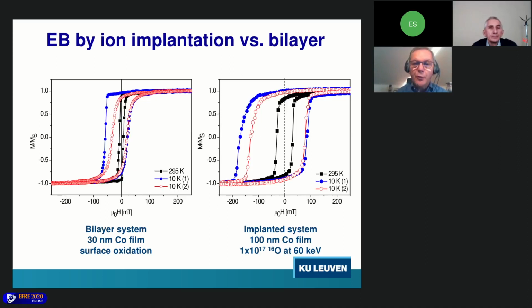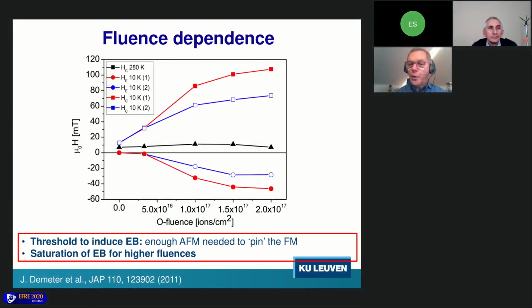So this is an interesting result, and we have then looked more into the systematics of it. For instance, here you see the influence of the amount of oxygen ions that we implant, so that is the fluence dependence. Here on the horizontal axis, you see the fluence of oxygen ions. And what is important here is to see that on the upper part of the graph, the coercivity increases when you put more oxygen into the layer. And here on the bottom part, this is the so-called exchange field. That is the amount of the shift of the hysteresis loop.